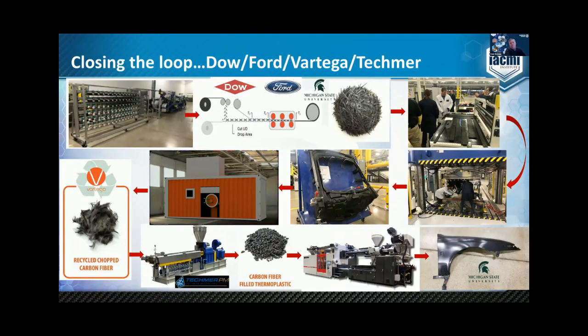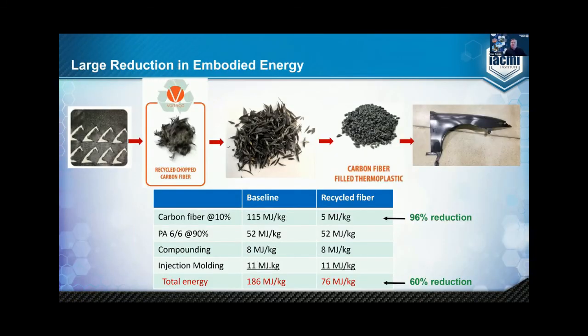We worked with Vartega. Remember the Ford liftgate, that material, any of that scrap material was sent to Vartega for recovering the fiber. It was put into thermoplastic pellets, sent back to Detroit, injection molded into fenders, so it made the complete loop. One of the key things here is when you do use recycled fiber, you can see pretty significant reduction in the amount of embodied energy that's in the fiber, and then consequently the amount of energy that you get in reduction for the finished part, in this case, the injection molded part. So big demonstration there on how to get embodied energy back out and reutilize a very important resource like carbon fiber.